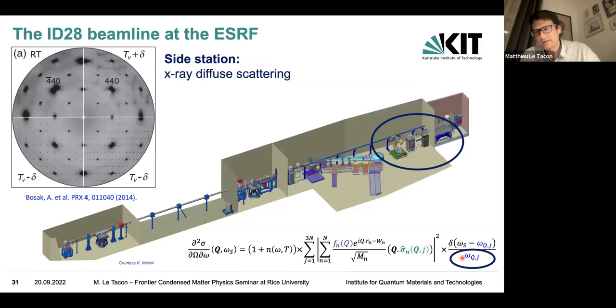The diffuse scattering is basically telling you that if you see some diffuse scattering signal, then you possibly have a soft phonon. That doesn't work every time, since you also have some static defects, but often when you have diffuse scattering, it actually corresponds to a soft phonon. So the strategy is to map the reciprocal space, find out where there is a lot of diffuse scattering, and then go there and do an inelastic X-ray measurement to see whether it corresponds to a soft phonon or not.